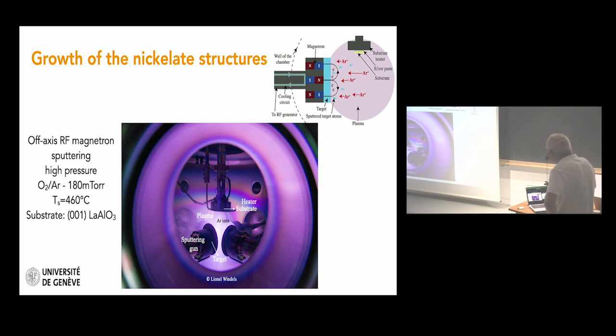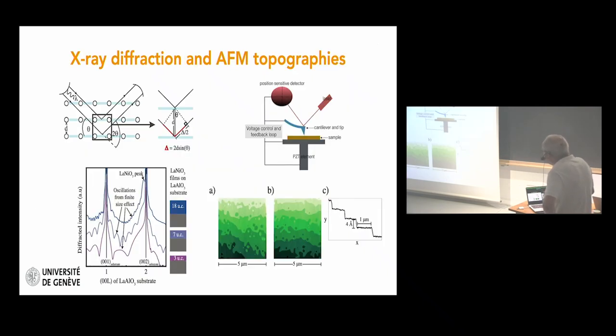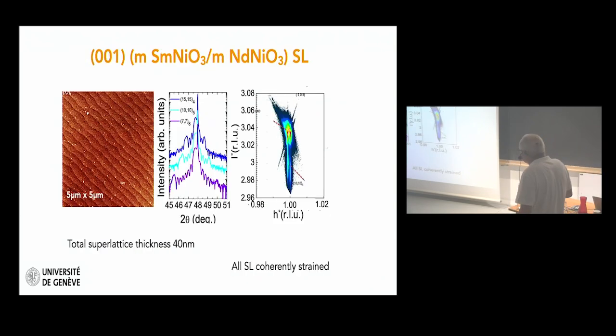If you have a question, I can answer. The characterization is mainly X-ray diffraction, atomic force microscopy, and scanning transmission electron microscopy. From X-ray diffraction, you can get the lattice parameters of the system. You can have an idea of the quality of the structure by looking at these fringes, which are linked to the finite number of diffracting cells. And from AFM, you see the surface. So this is typical characterization.